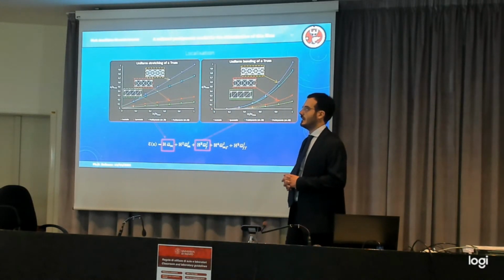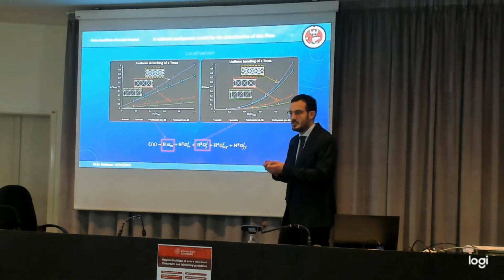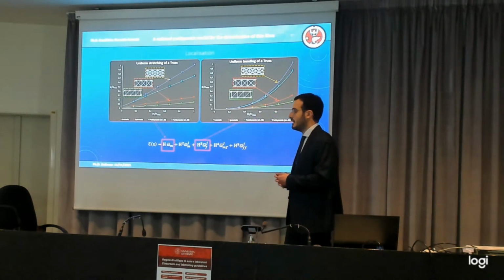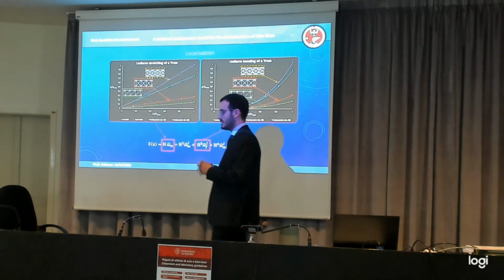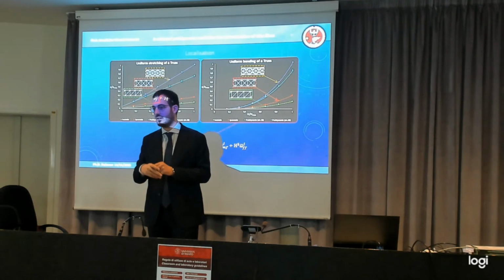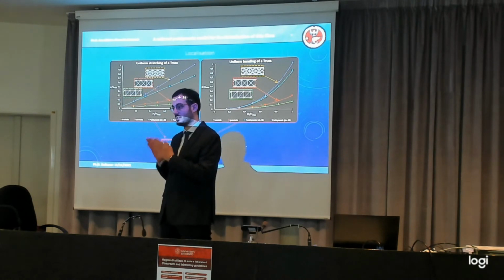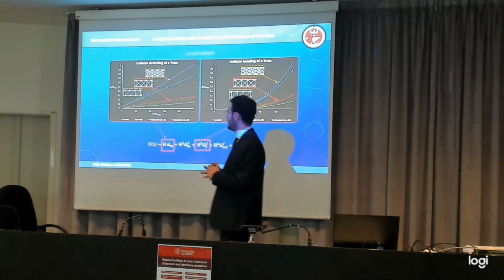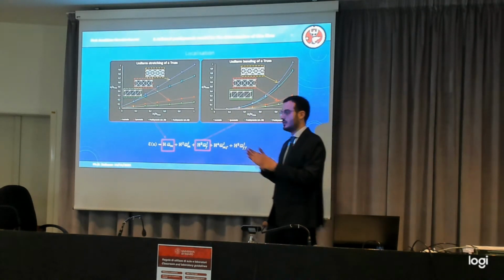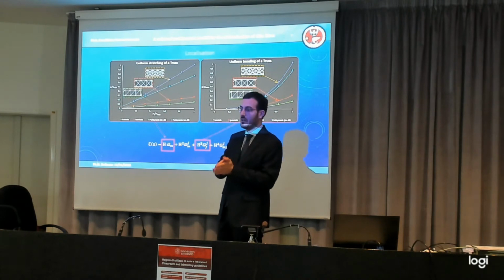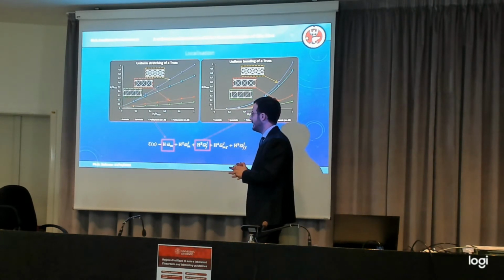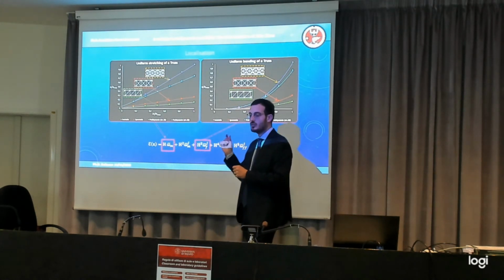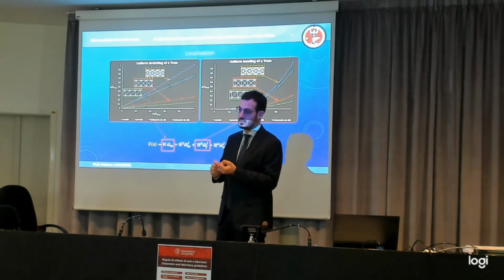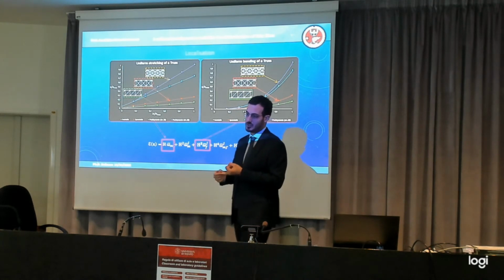Those two parameters need to be calibrated each time that you define a refinement. In particular, if you want to reproduce a specific behavior, for example that of glass, which has a fixed Young modulus and breaks consuming a certain defined amount of energy, you use energetic equivalence between your numerical discretized model and the analytical local solution. There are two very easy formulations that you can use to calibrate these two parameters in order to have the same overall stiffness, which is what you want, and the same overall consumed energy for fracture development.